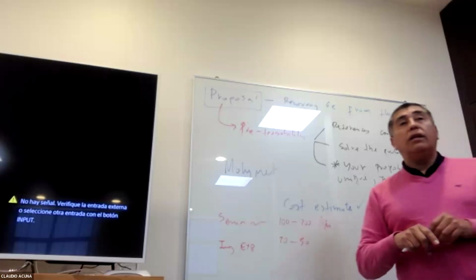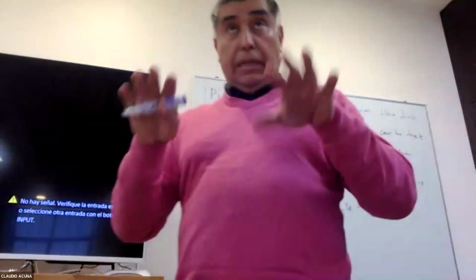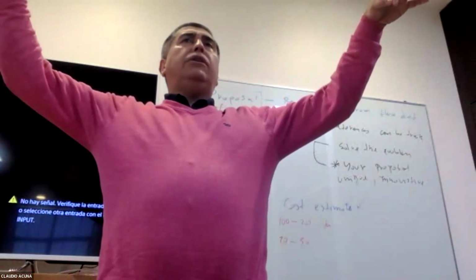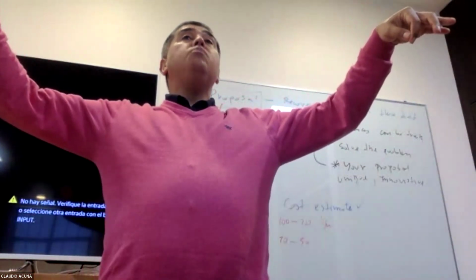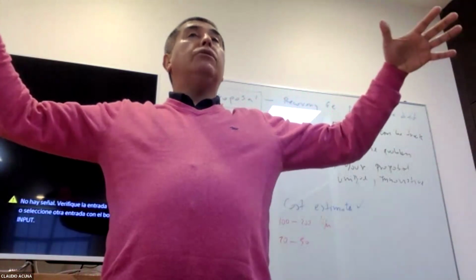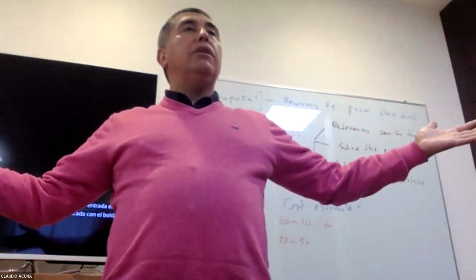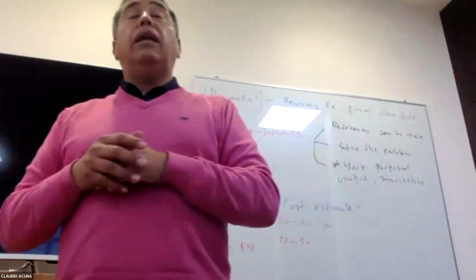We have characterized all the tailings, not all, but most of the tailings in Chile. But all of them are made at 2 meters depth, and they assume that it is homogeneous. And tailings is not homogeneous, definitely. We have another work on that. It's heterogeneous in particle size, it's heterogeneous in liberation, and also in element composition. So the most difficult thing for the final project will always be sampling.